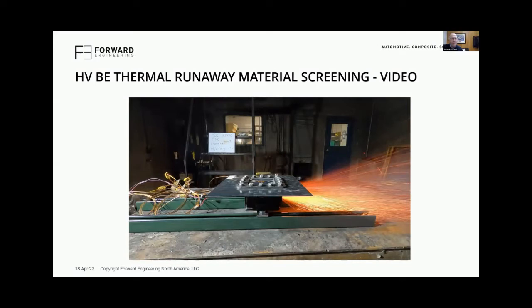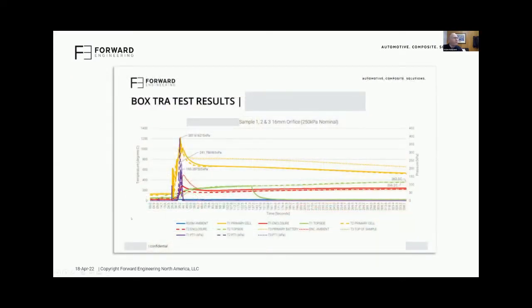that event. Again, being sensitive to time, we can see these curves here, and this is the type of data that's generated from the reports. We have temperatures that the samples are being exposed to, 1,000, 1,200 degrees, that nominal pressure that's being imparted on that sample inside that enclosure, a low of nominally 200 kPa up to almost 400 kPa with the nominal 240 kPa. Topside temperature, this green line showing you the temperatures on top of the sample.